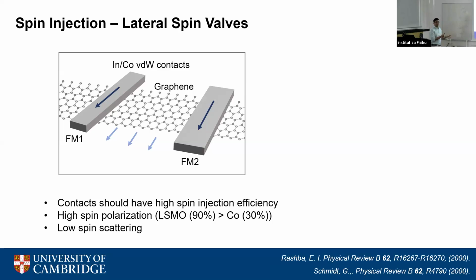And you see if there's any difference in the resistance because of the spin orientation of the two contacts. Now, the challenge in this field is that it sounds very straightforward. You put two ferromagnets and you measure the resistance. But you have to introduce spins from this ferromagnet to graphene, which means that these contacts should have high spin injection efficiency. So we know that we have magnets like iron, cobalt, nickel, but these magnets have certain polarization.